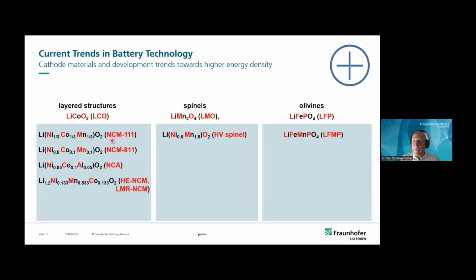Maybe you have heard from NCM materials. The driver is to replace the expensive cobalt and reduce it to 1/3 or even to only 10%. And this is, let's say, a material up to date with 80% nickel, 10% cobalt, and 10% manganese, abbreviated to NCM 811. This is very similar to the NCA, the lithium nickel cobalt aluminum oxide, which is made by Panasonic for Tesla. And for the future, we have lithium and manganese rich NCMs.